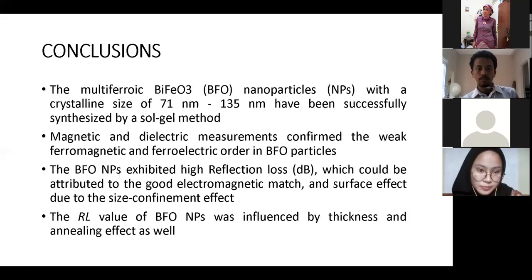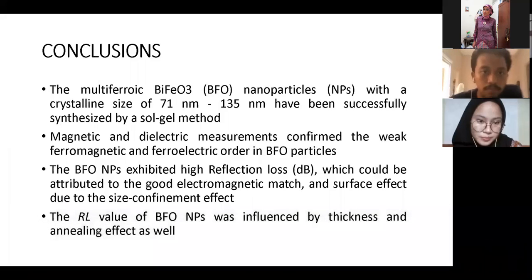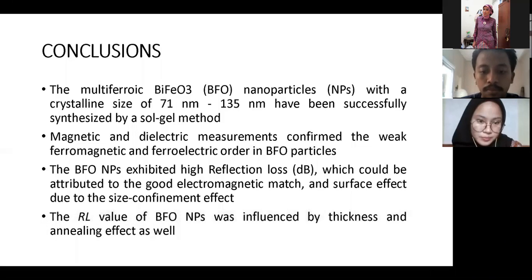Conclusion: the multiferroic bismuth ferrite nanoparticles with crystalline size of 71 nanometers to 135 nanometers have been successfully synthesized by the sol-gel method. Magnetic and dielectric measurements confirm the weak ferromagnetic and ferroelectric order in BFO particles. The BFO nanoparticles exhibit high reflection loss, which could be attributed to the good electromagnetic match and surface effect due to the size confinement effects. The reflection loss value of BFO nanoparticles was influenced by thickness and annealing effect as well.